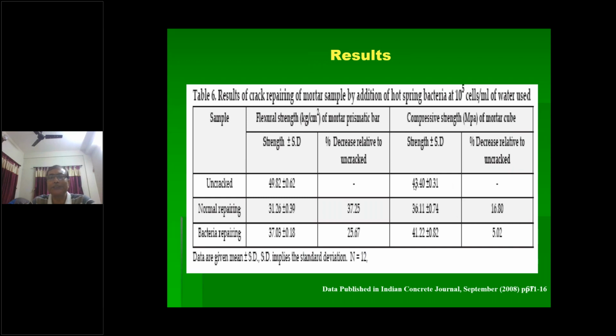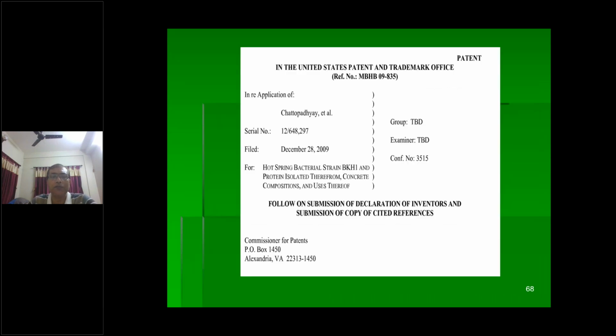But if we come to the compressive strength, initially it was 43 when there was no crack. Cracked with a normal repair, it comes to 36. It's quite less because of normal repairing. But when it is repaired with bacterial concrete, we are getting almost 40, which is almost similar to the normal strength. On the basis of these results, we have got a US patent for the hot spring bacterial strain, BKH1, and the protein isolated from it, used in concrete composite.